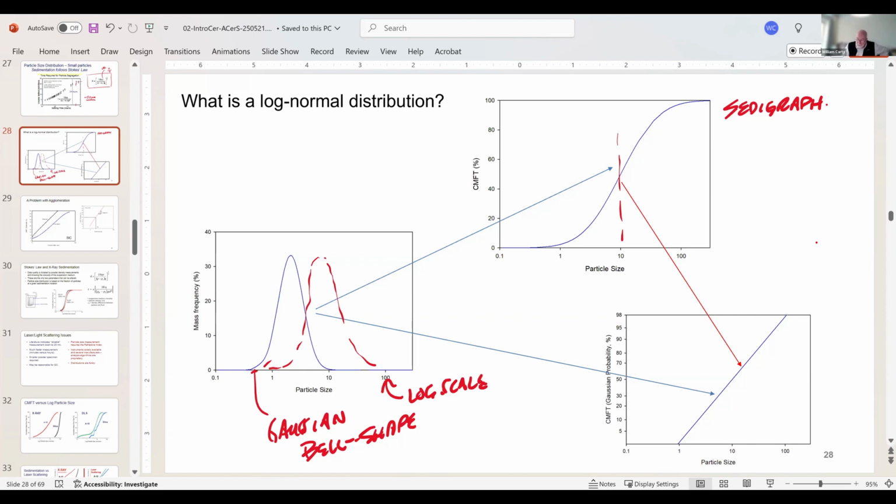We started working with this several years ago. If I get what's called a probability axis, this is a probability axis, and I do, it is a Gaussian curve like this in terms of the scale. If I take this data and I plot it here, I get a straight line. So our thoughts were that we could characterize this distribution by a mean, this is my D50, and a slope. This is the width of my distribution. Okay, we're still working on that, but this is what it means to be log normal.